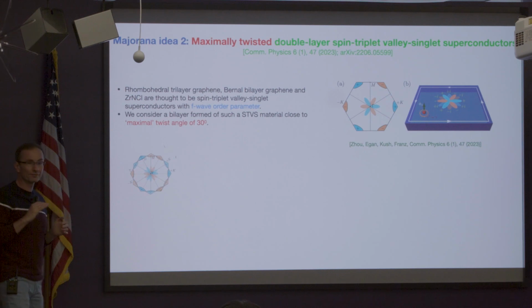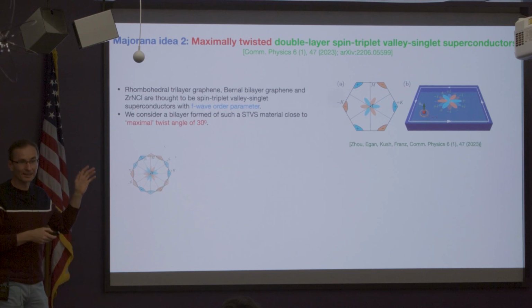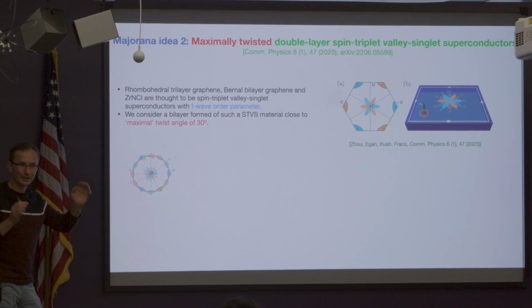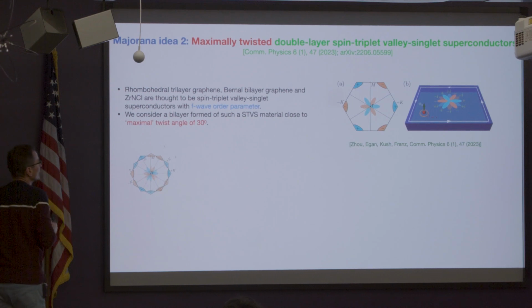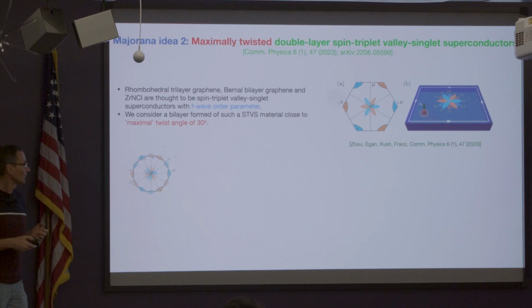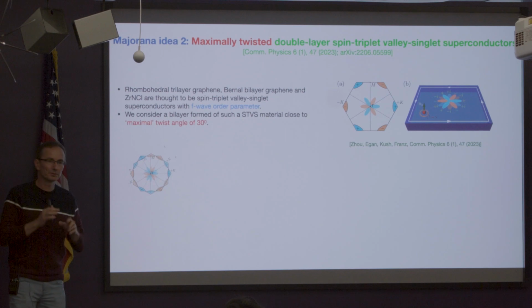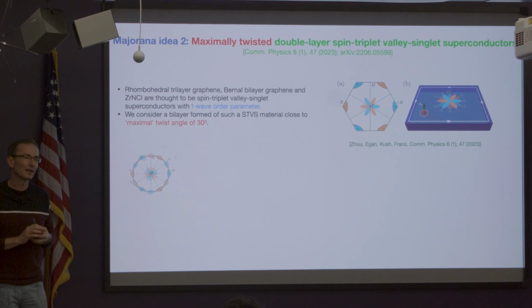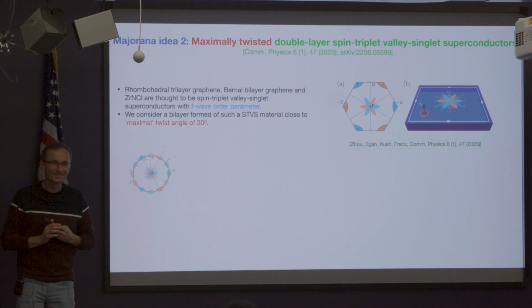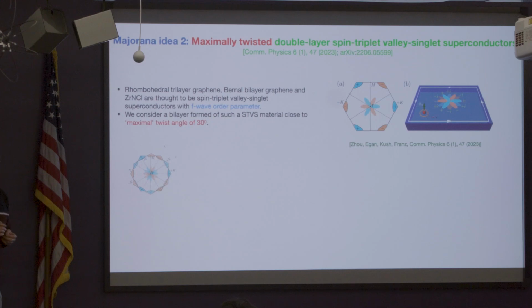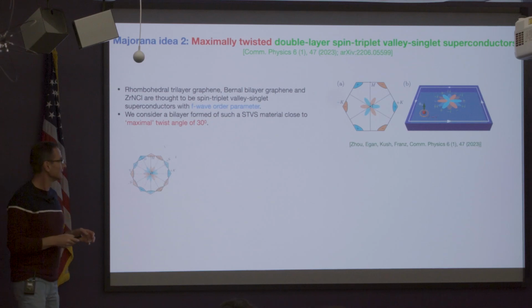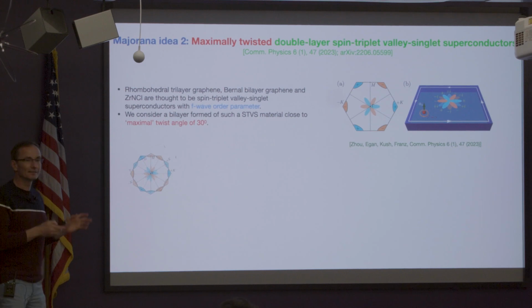We haven't really considered the effect of in-plane field. You could argue that it may be detrimental to this. On the other hand, this is not Pauli limited, right? So in-plane field doesn't kill the superconductivity. Rather, it creates it. So from that standpoint, you may think it will not really disturb this putative F plus iF prime state, although we haven't modeled that. We just did a zero field calculation, which was complicated enough for my postdoc. Well, it was his idea. I told him this is going to be hard, and he said, OK, I can do this.